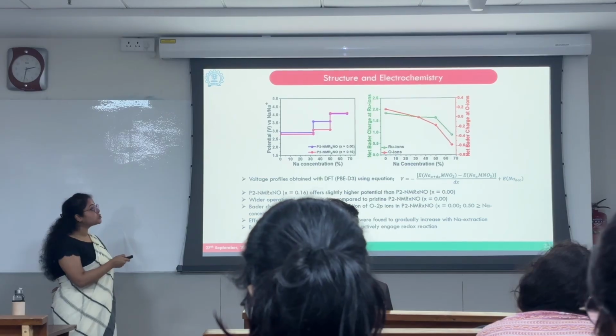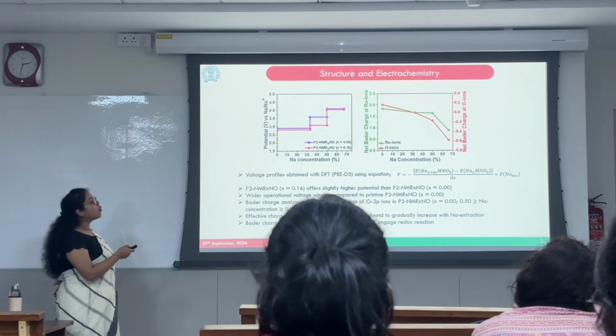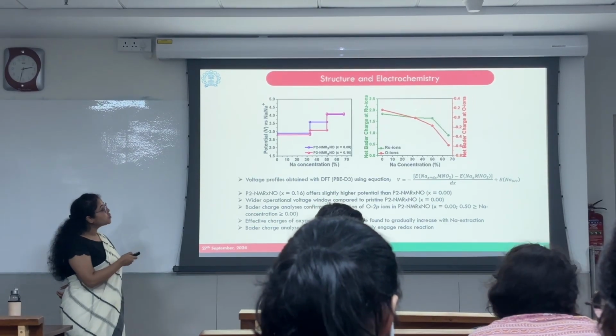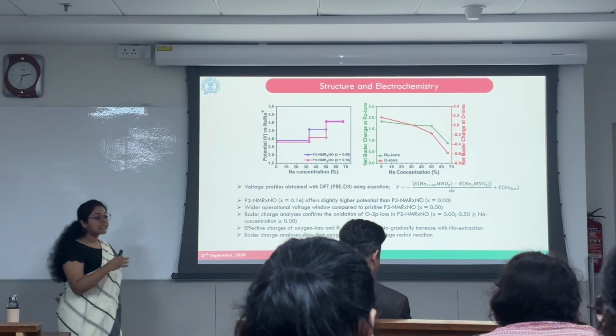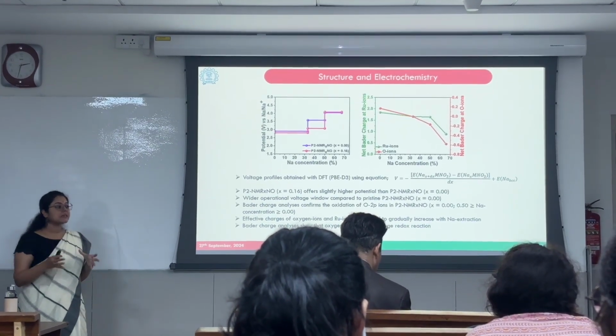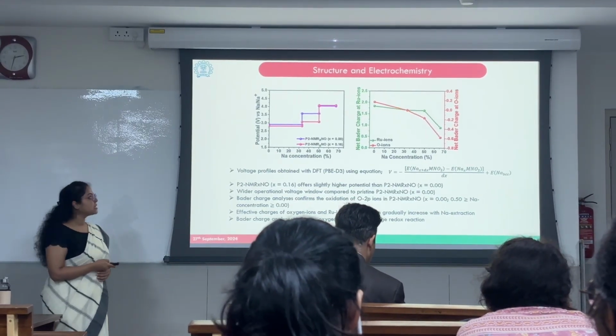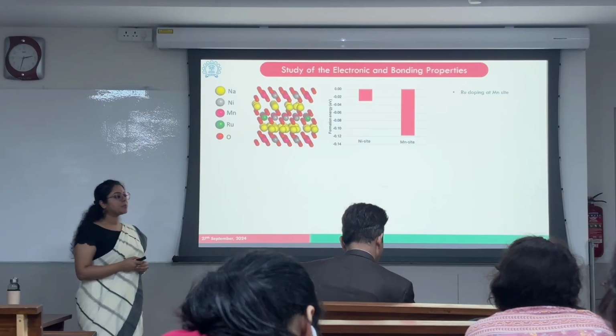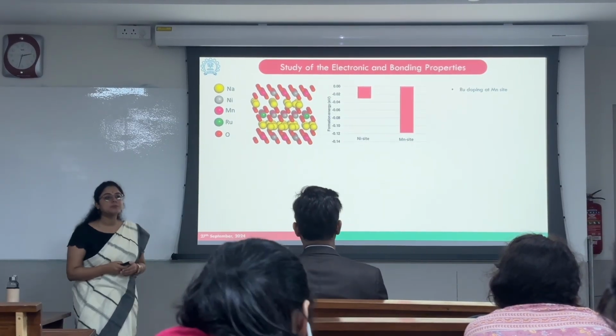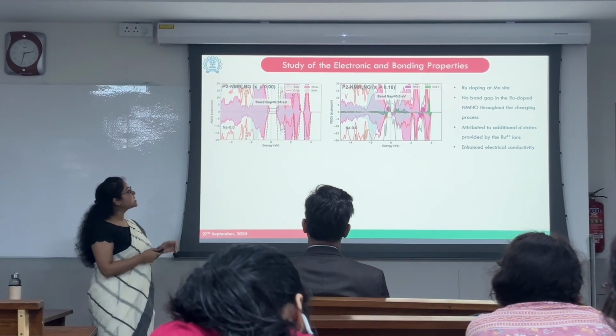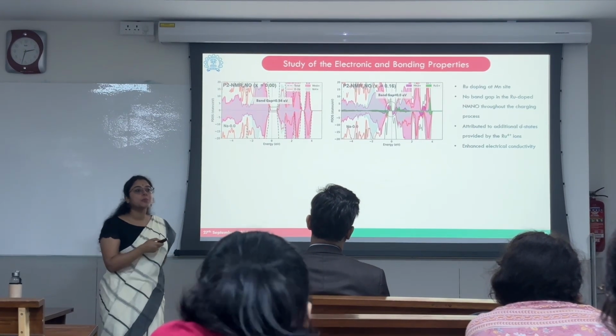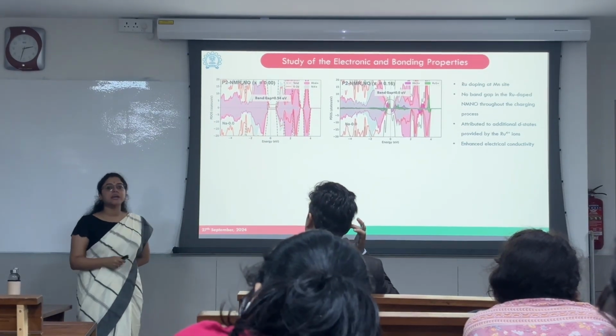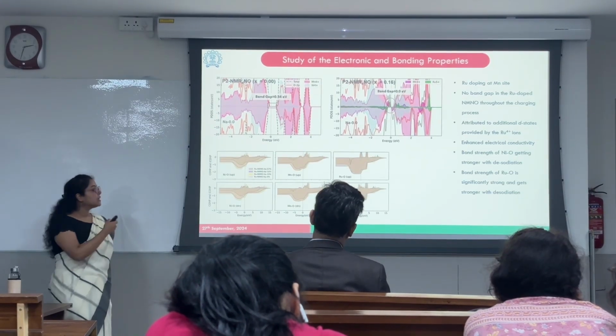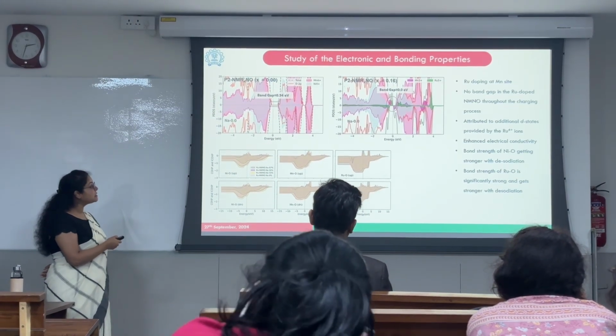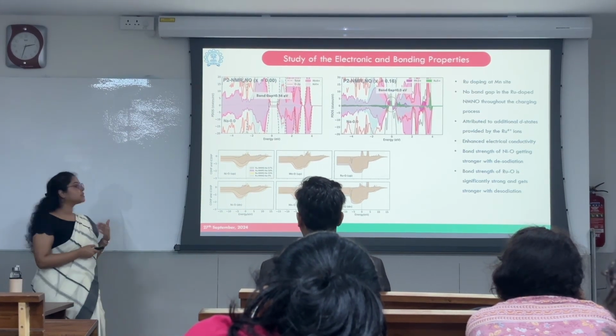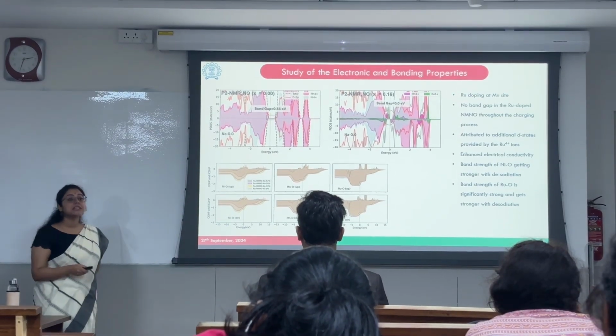However, what is important is the Bader charge analysis, which confirms the oxidation of O2p, and it was also seen that the ruthenium ion and the oxygen ion activity increases with desodiation. So it tells us that oxygen is actively involved in the redox process. Further, to study the electronic and bonding properties, we conducted the DFT analysis and saw that ruthenium is doped on the manganese site. Through the calculation, we observed that the band gap was 0 electron volt after doping ruthenium, which can be attributed to the d states provided by the Ru4+ ions. And through the COHP calculation, we saw that the nickel, manganese, and ruthenium oxygen bond strength increases with desodiation, and the ruthenium oxygen bond strength is significantly strong.